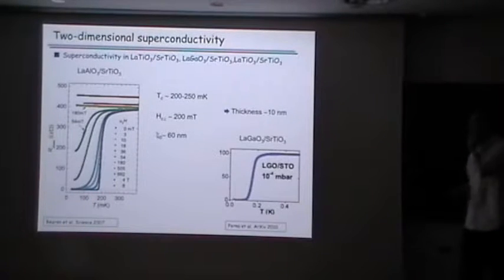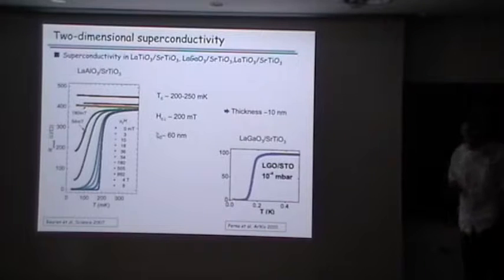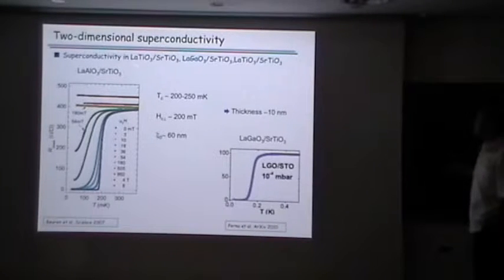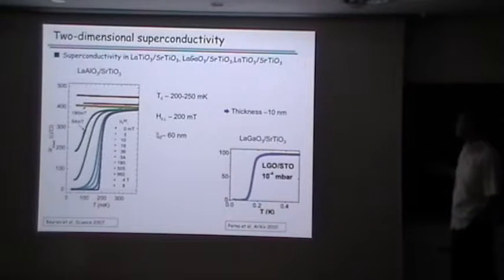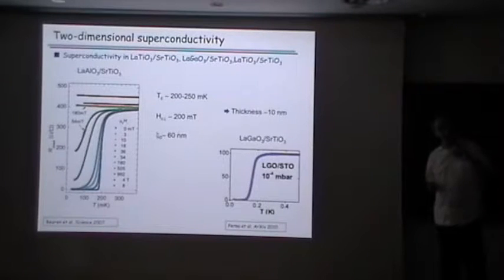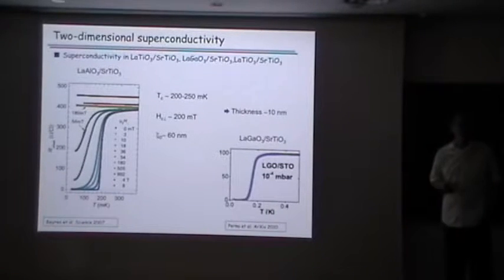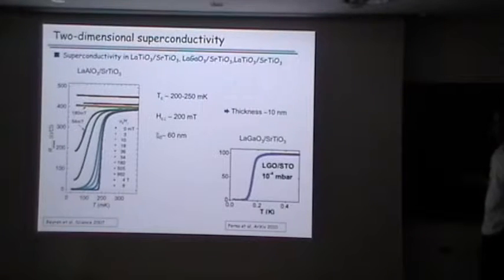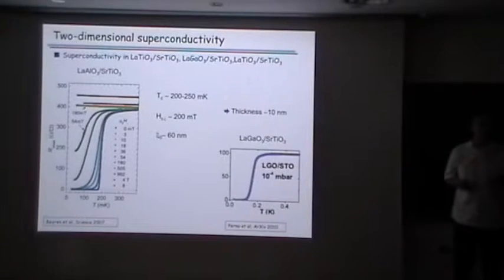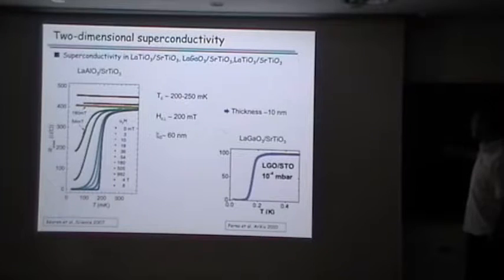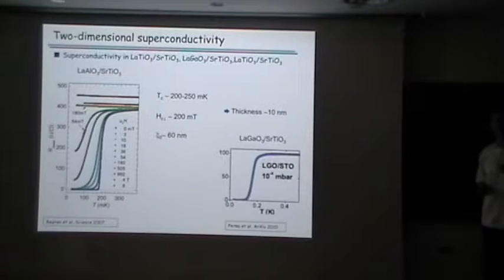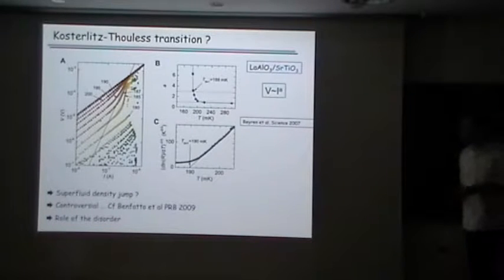Okay, so whatever the type of heterostructure you grow on strontium titanate, lanthanum titanate, lanthanum aluminate, and so forth, if you get the two-dimensional electron gas, in most cases you also get superconducting behavior. So remember, doped strontium titanate itself is a superconductor, and the TC that we get from this type of superconductivity is also in the same range as the strontium titanate TC.